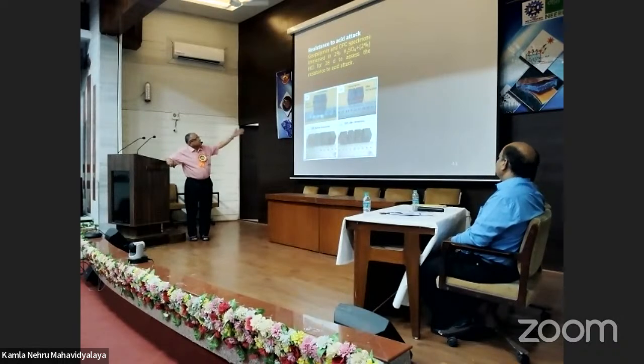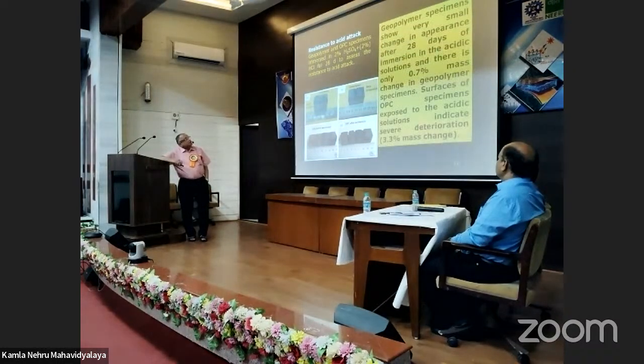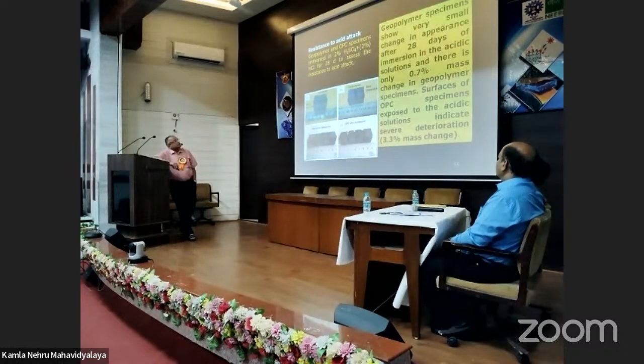Now, durability. Normally, concrete structures are not durable in acidic atmosphere. So, you see that we take Portland cement mortar or concrete, and geopolymer cement and concrete, and put them in 2% sulfuric acid and 2% hydrochloric acid for 28 days. Then what do we see? Geopolymer specimens show very small change in appearance after 28 days.